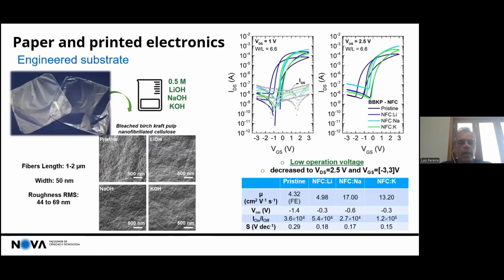We also developed some specific paper substrates that, as I've said, in this case, also work as a dielectric. So, based on nanofibrillated cellulose that we can dope with different ions, so make a kind of ion doping to improve the ionic conductivity of the paper substrates. And you see here how you can really improve the performance, strongly reducing the hysteresis, but most importantly, reducing the operation voltage by 1 order of magnitude. So just the optimization of the dielectric itself introduces a huge improvement in the performance of the devices. So we can reach mobilities on these films that surpass 15 square centimeter per volt per second.